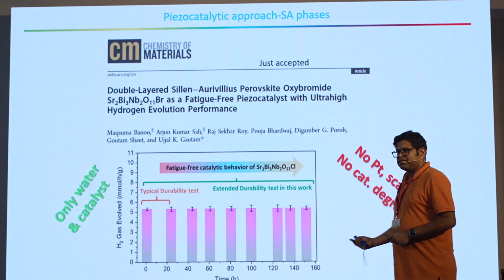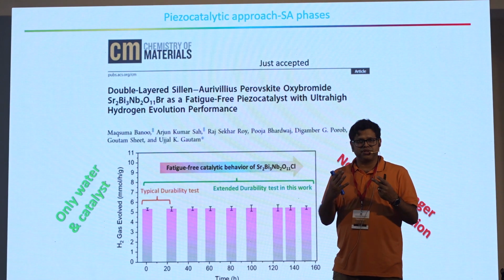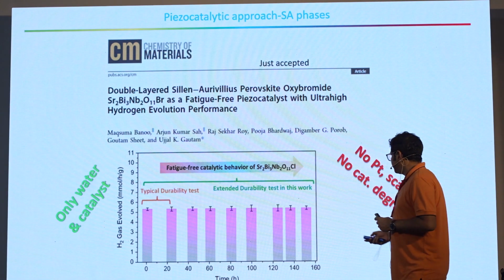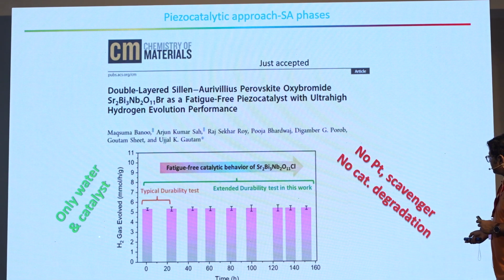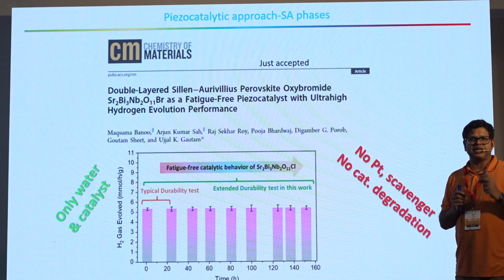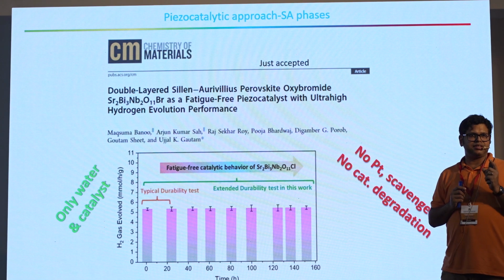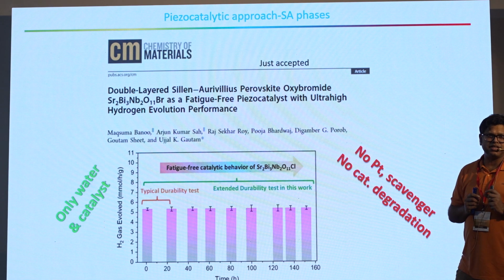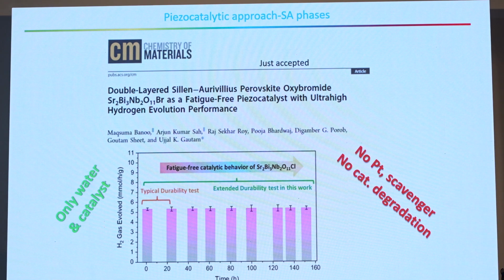This is another very interesting work, again about green hydrogen production. You see that this is a plot showing hydrogen evolution, and this is used for a very long time. Normally it stops somewhere here, but it shows no degradation. Using these Sillen Aurivillius phases, again I am not going into the details of why it happens. It is something called space charge neutralization, which happens in these crystals. So you get hydrogen evolution for a very, very long time.